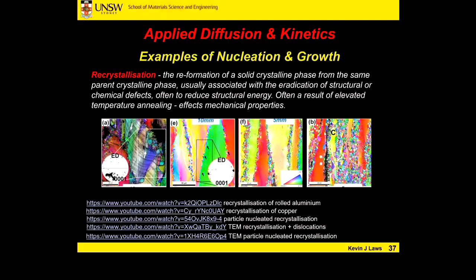All right. When we deform a metal, we cold work it. Okay, we cold roll it, hot roll it. We start to deform those crystals. We create defects in the crystal structure in the form of dislocations or vacancies. These dislocations and vacancies are high energy. We're destroying that crystal structure, which is the lowest structure of the material. By inducing these defects, we're increasing the structural energy. If we get enough dislocations and imperfections in our crystal, they then become sites for new crystals to form locally from that site. We will have a big lecture set on recrystallization in week 9, I think it is. So that's something that we can also think about for our recrystallization.